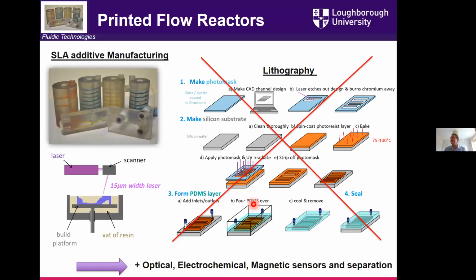That was cool and trendy. And so we weren't looking to generate these sensors via typical lithography. We wanted to lean on the additive manufacturing processes that we had here at Loughborough. And so what I'm going to show you are some examples using SLA additive manufacturing, where you build up, layer by layer, the features of your fluidic chip and sensor by using a scanner to set and polymerize a resin. And you build up the features that we're going to go through.